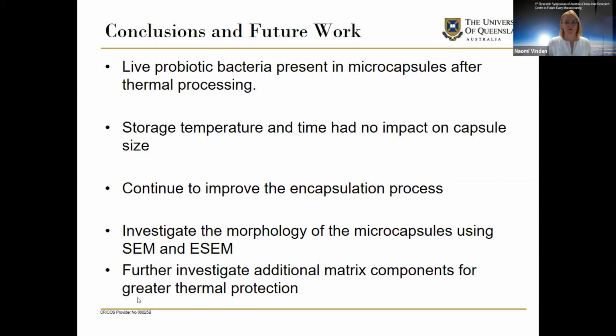I want to investigate the morphology of the microcapsules using SEM and ESEM, and to further investigate additional matrix components for greater thermal protection, which I have just initially started. Hopefully the ImageJ software and Z stacking using CLSM will allow me to get some actual numbers for the heat treated yogurt and milk samples. So far it is looking fantastic, and I have yogurt that has probiotic bacteria in it after thermal treatment. This is what I'm aiming for, and so far so good.